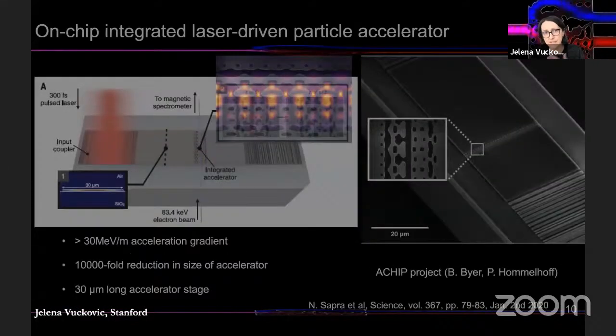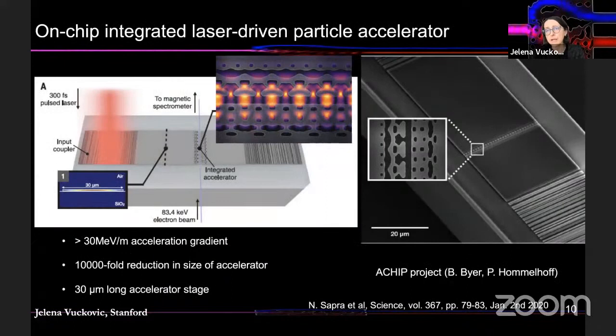So once we designed it, we fabricated it in silicon for an incoming laser with 2 micron wavelength. So this is a 300 femtosecond pulse laser. We also inverse designed these couplers so that they have a large bandwidth, so that they could couple these very short pulses without loss, and also not melt, because this is a very energetic pulse. The laser beam would propagate here, get coupled to this structure. Electrons with 83.4 kilo electron volt energies are coupled to the vacuum channel, and then we characterize them at the output.